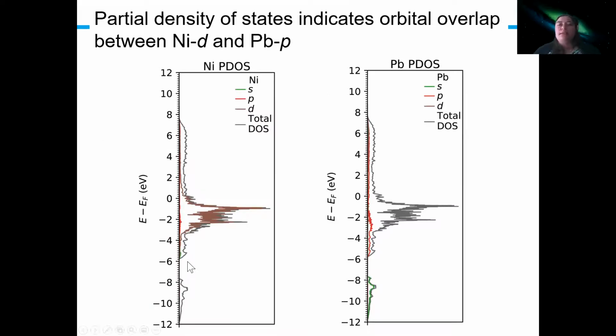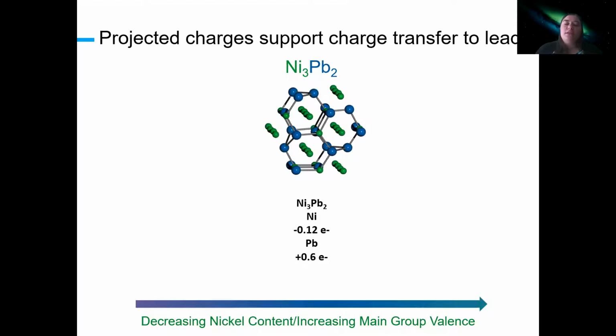And we also see, looking at the density of states for this material, that there is predominantly nickel d and lead p, which means that there's going to be the opportunity to have some overlap and some bonding there. And then, just out of curiosity, one of the things that I wanted to do was look at the projected charges for this structure. This is a theoretical technique for identifying how you assign the electrons between the different elements in your structure. In comparison to the elemental structures, what we see is that we have lost some nickel electron density and gained some lead electron density. So this is also consistent with our picture of charge transfer.